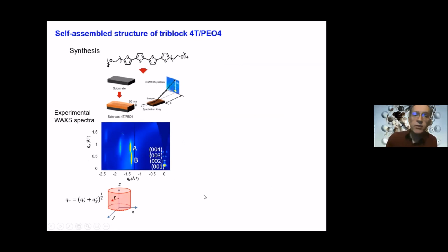Now, we wanted to do also simulations. In fact, the simulations preceded some of these experiments. But it turns out that if you just use molecular dynamics and you throw into a box hundreds of these molecules using an atomistic force field, you can wait months and almost nothing happens. It doesn't assemble. So the time scales are really off. You need to do something about it.